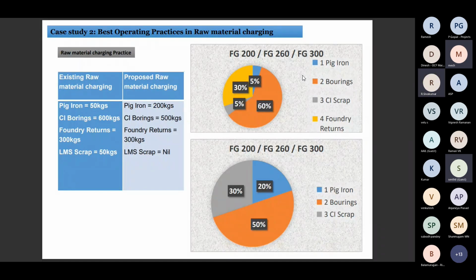Next one is the same thing, best operating practices in raw material charging itself in another foundry. This graph shows the existing charge: pig iron 50 kg, CI borings 600 kgs, foundry returns 300 kg, LMS scrap 50 kgs. The furnace capacity is almost 1 ton, 750 kilowatt. The proposed raw material charging is first pig iron 200 kg, then CI borings, foundry returns and LMS scrap. So the pig iron quantity is increased. Earlier they used only 5%, now it is increased to 20%, 5 to 20%. Next one.